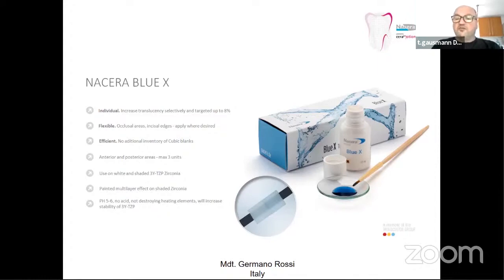It is limited due to the fact that this is real yttria. This is nothing else. It is real yttria. So you are doping the material and you're changing the internal structure. And you can see in this little picture that it goes from less translucent to much more translucent. So you're changing the material yourself from 3 yttria, normal tetragonal material, to 4 yttria material. So you don't need to change the whole disc and weaken the whole disc. You're just changing only partially the disc.